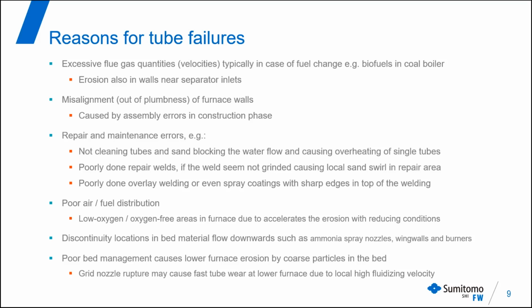Furnace walls out of plumbness, misalignment, causes also problems from an erosion point of view, because when the bed material is flowing downwards on the furnace wall, if it's misaligned, then the particles will hit the wall and the tube will start to erode. Maintenance errors might also relate to the local increased erosion of the tube, if the shape of the tube is not ground to be as close to original as possible, because this kind of discontinuities in the tube will start a swirl of material in that location, and the erosion will be fast there.